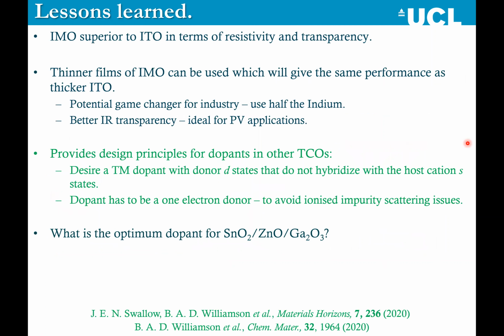So the lessons that we learned from this type of study was that IMO now is, we believe, superior to ITO, and thinner films of IMO can be used, which should give the same performance as thicker ITO. So we believe that this is actually a really big deal for industry, because you could use half of the indium to get the same performance as people are doing for ITO. But also you have this better IR transparency, which is actually ideal for solar cells because you want to reduce the parasitic losses in the IR in any devices.